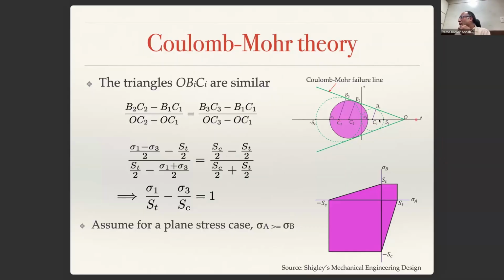So OC3 minus OC1 can be written as SC by 2 plus ST by 2, because if you start here, OC3 minus OC1, we are actually talking about this distance, the C1 to C3 distance. Is that correct or not? Yes, sir. So the C1 to C3 distance is this distance plus that distance. This is SC by 2 and that is ST by 2. Is that clear? The distance between C3 and C1 can be seen as the distance between C3 and the origin plus the origin to C1. So origin to C1 is ST by 2, because this is the radius of this circle. C3 to origin is the radius of this big circle, that is SC by 2. That is what we have written.